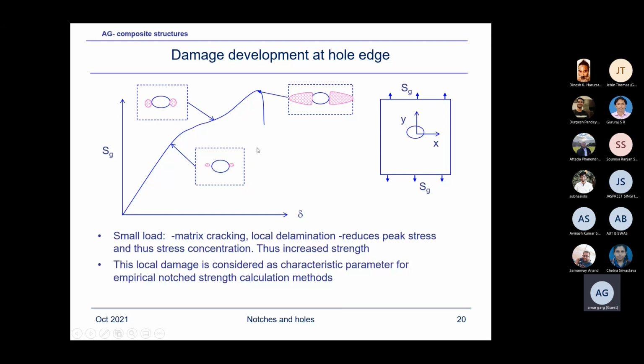Now, if you compare this with a metal, a similar thing will happen, because right at the edge of the hole or the crack tip, there would be higher stresses. So the material starts yielding, and the yielding will spread across the net section, which will relieve the stress concentration and provide the final failure, which would be at a much higher stress compared to Kt sigma value in an isotropic material. The same thing happens in composites. This phenomenon does relieve the stress concentration factor. For the smaller holes, the effect is more, and that is why the residual strength is higher than considering Kt sigma.